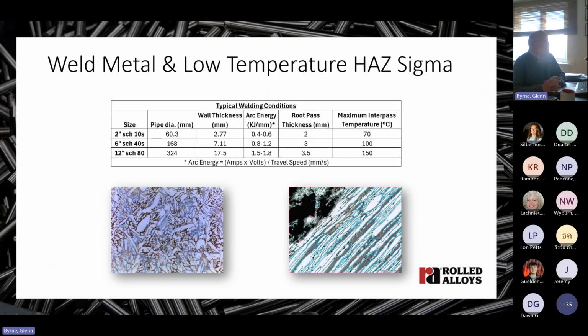Now, we can also get sigma in welds. It's possible to overheat the weld with excessive heat inputs and interpass temperatures and then form sigma phase in either the weld metal or low temperature heat affected zone, or both. In the case of the low temperature heat affected zone of the pipe, the 850 to 900 degree isotherm in the pipe is the location where sigma phase forms first and fastest.